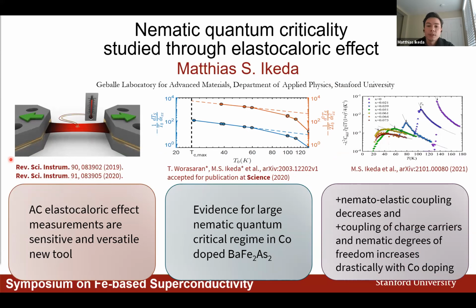And a couple of take-home messages from my presentation are going to be that AC elastocaloric effect is, as I mentioned before, a quite simple, beautiful, and versatile technique that really calls for widespread application in the field. And then also, as mentioned before, we find evidence for a large regime in the phase diagram for cobalt-doped barium iron arsenide that is governed by nematic quantum critical fluctuations. And then finally, through our elastocaloric effect measurements in the B2g strain channel, we find that the nematoelastic coupling decreases, but the coupling of the nematic degrees of freedom and the charge carriers increase drastically as we increase the cobalt concentration coming from the underdoped side.